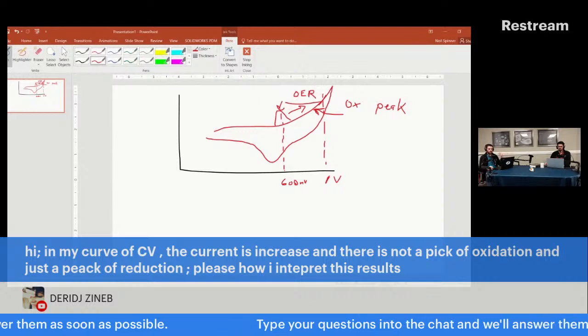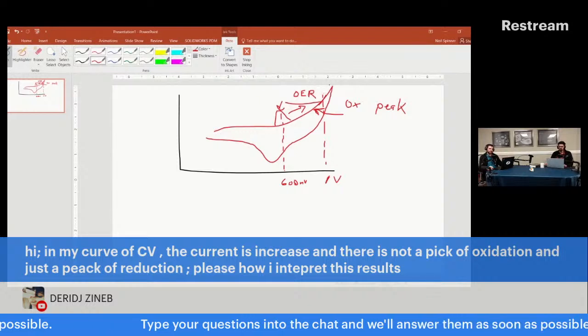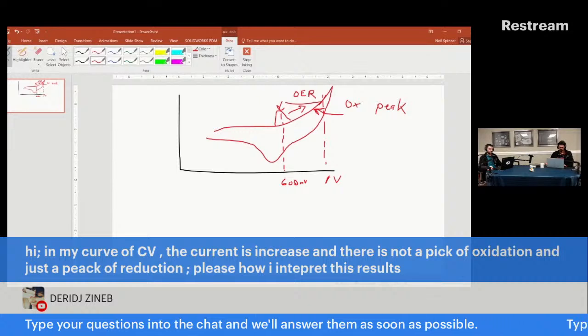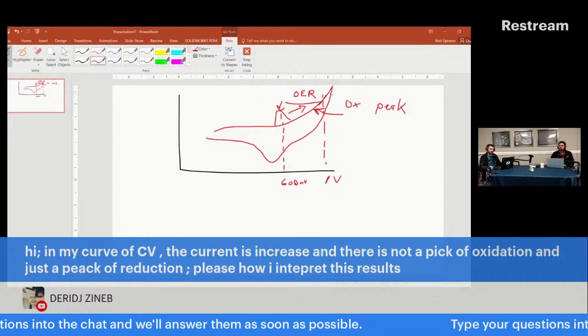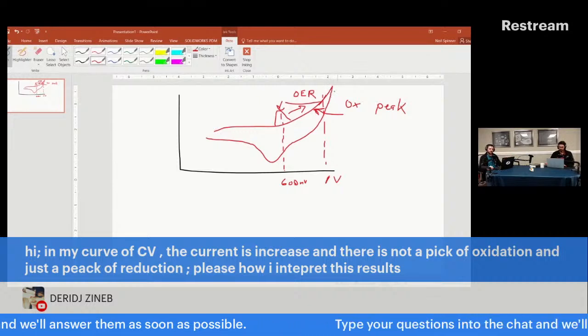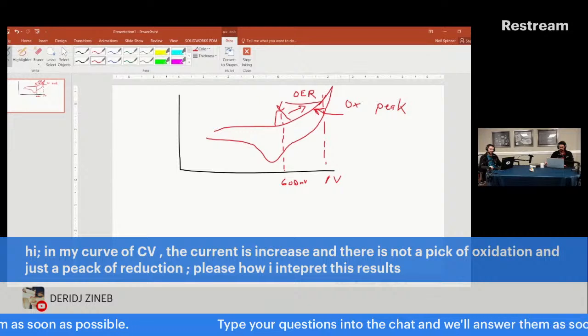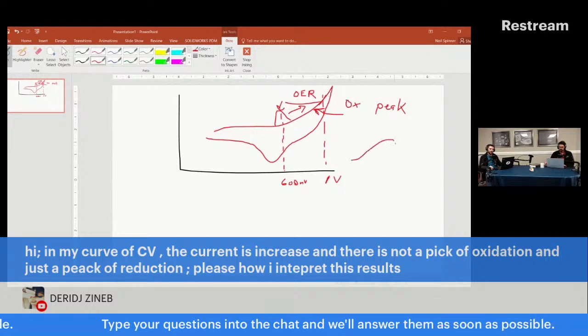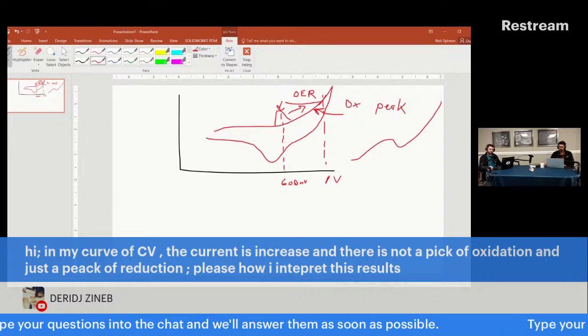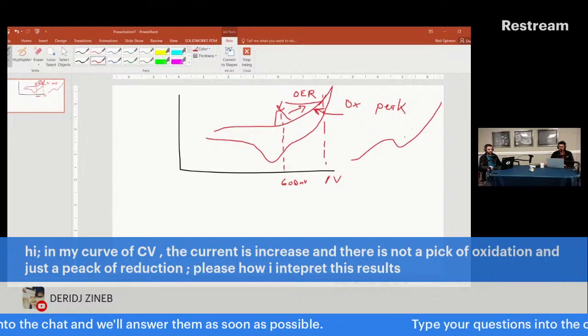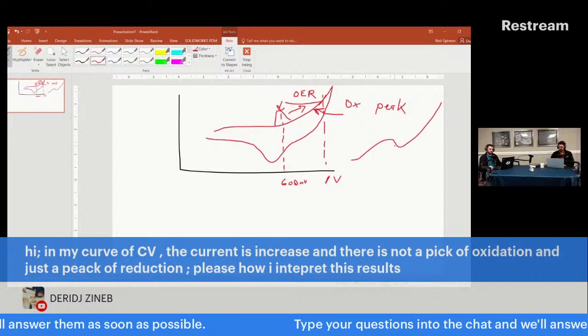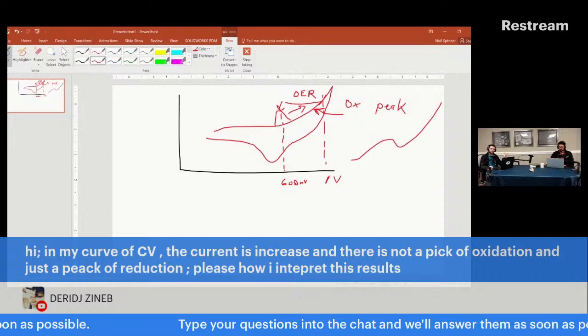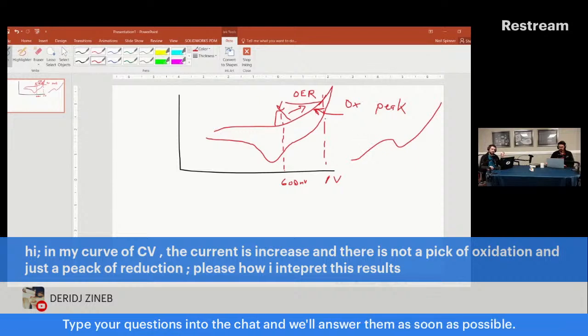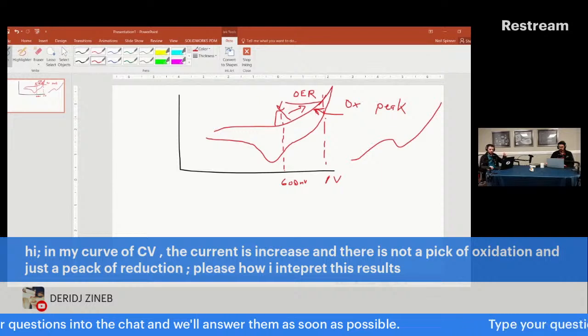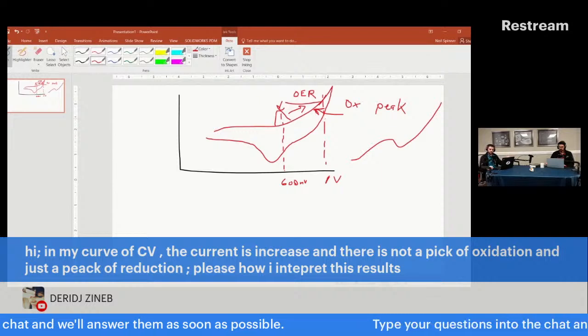Assuming water, you're at the limit of your electrolyte stability, and you're just going to keep ripping oxygen out in the oxygen evolution reaction. Sometimes if you scan fast enough, you can kind of get a peak out of it on its way towards more oxygen evolution. It's a little bit of a difficult thing to do, but that might be what you have, is that the oxidation is just convoluted within something else, like the oxygen evolution reaction.